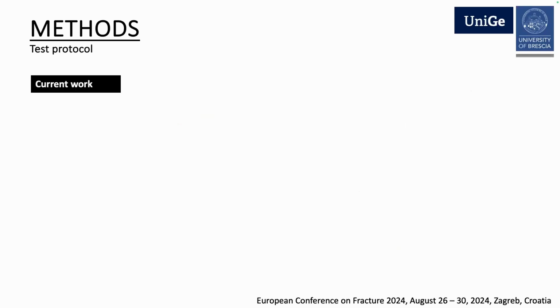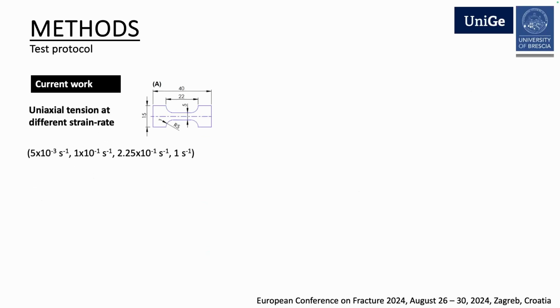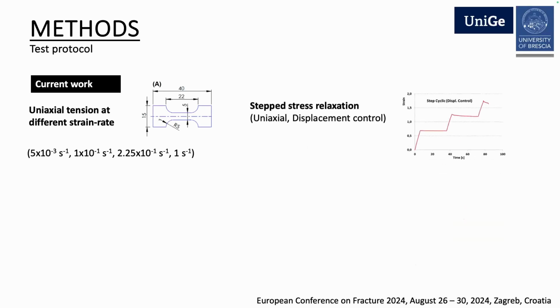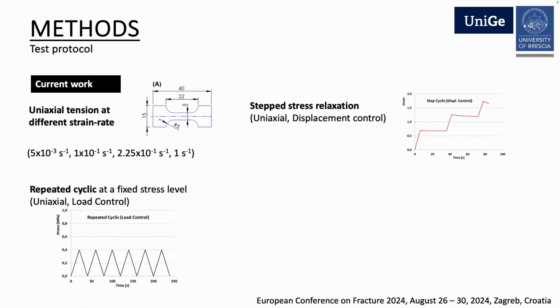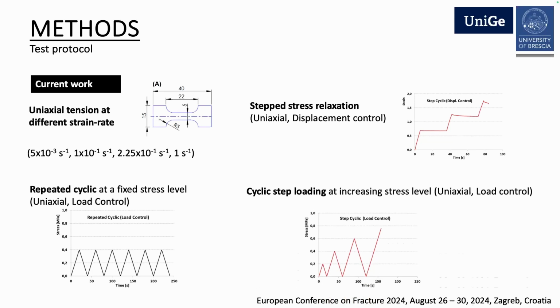So what we have done in the current work is a less, let's say, conventional characterization. So we characterize the time-dependent response. We combine uniaxial tension tests with different strain rates and step stress relaxation tests. So we have a stress relaxation, but at increasing load levels. For the cyclic response, we carried out tests with repeated cycles, either over a fixed stress level or with a stepped procedure in which the load level is progressively increasing.